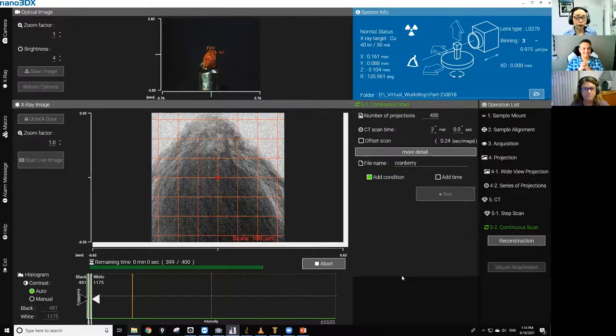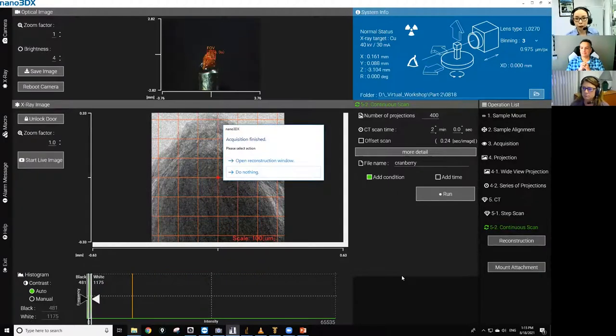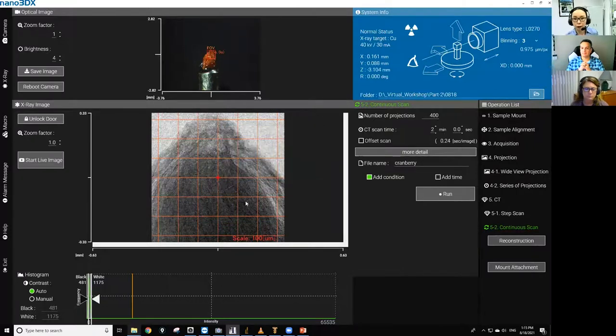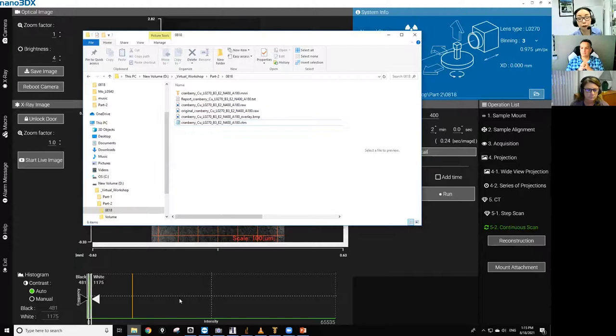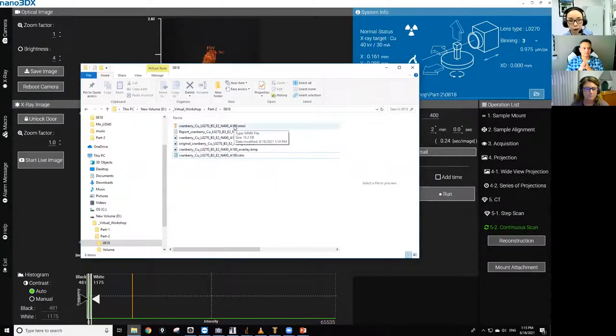It essentially comes down to the voxel resolution that you need to see whatever feature or details you're trying to image. If you need, for example, a quarter micron voxel resolution, you have to stick with a 20x lens, because even with binning one, that's the voxel resolution you have, a quarter micron. But if you need only, let's say, half a micron resolution, then you can change the lens to 10x and do a binning one scan, which will give you about half a micron voxel size. But you're doubling the field of view by changing the lens. So if you can afford to use a little bit larger voxel size, you can change the lens to cover a larger field of view in one shot. I hope that answers the question. We will have more time to address questions when we do more scans.